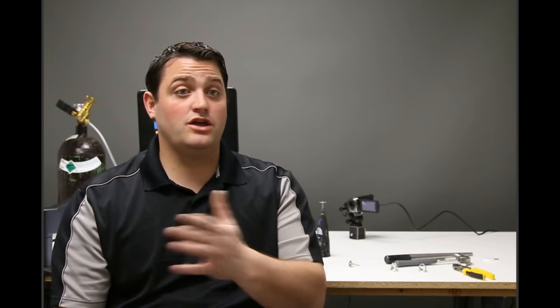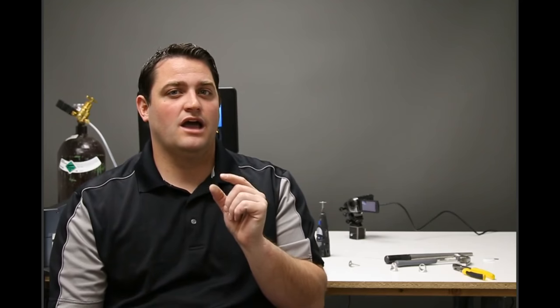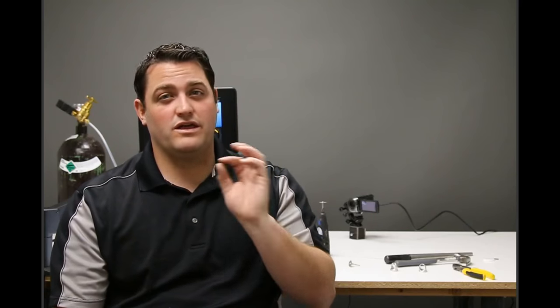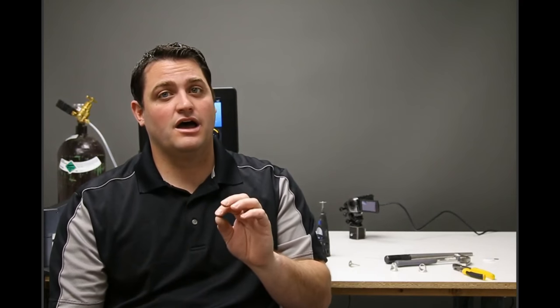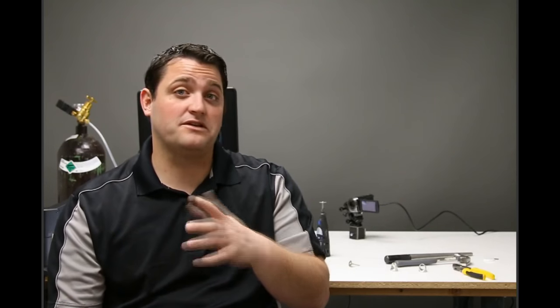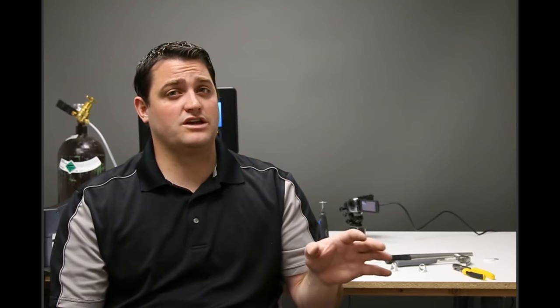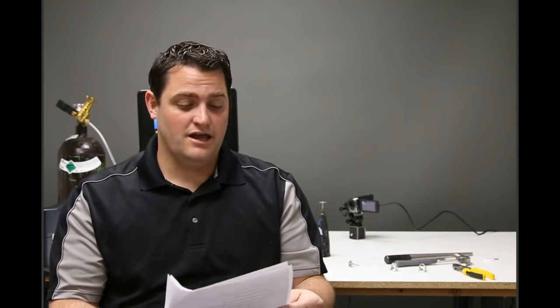And then same thing, you want to make sure with a laser you're using the right wire. A lot of our users use a variety of wires, but the one wire that I've heard stick out there is a silver with about a 5% platinum. That allows for better adding, and it cuts down the reflectivity just a little bit. So again, if you can get wire in approximately 28 gauge, that silver wire with about a 5% platinum added to it, a lot of the jewelry supply companies can help you. A lot of the tool guys, you can call in and ask them, and they can get you the right wire. But that's one specifically that I've heard people have had great success with when using on a laser. So it's just something to be aware of.